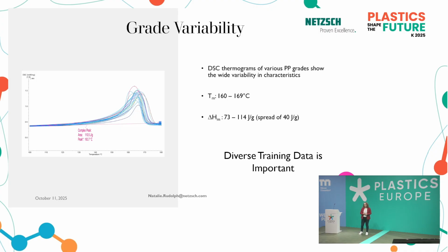So this shows great variability. Now I talked about the influence of the measurement. Now I'm talking about the influence the material supplier has in generating materials that are very fit to one purpose. This is showing the melting peak of 20 polypropylenes, or 25. And you see they all look different. The area under the curve is different. The peak can be here or here, so we have a variability of up to 10 degrees C in that peak temperature, and we have a spread of enthalpy between 73 and 114 of the data we had.